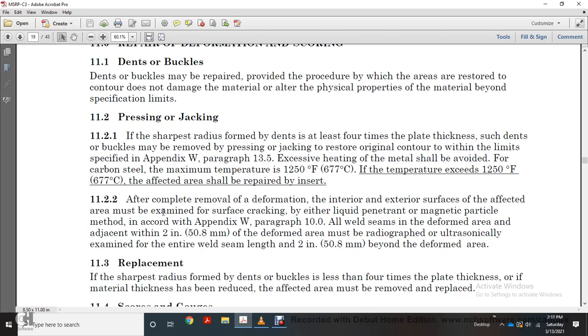Excessive heating of the metal should be avoided for carbon steel. Maximum temperature is 1250 degrees Fahrenheit, 677 degrees Celsius. If the temperature exceeds 1250 degrees Fahrenheit, 677 degrees Celsius, the affected area shall be repaired by insert. After complete removal of the deformation, the exterior and interior surfaces of the affected area must be examined for surface cracking by liquid penetrant or magnetic particle method in accordance with Appendix W, paragraph 10.